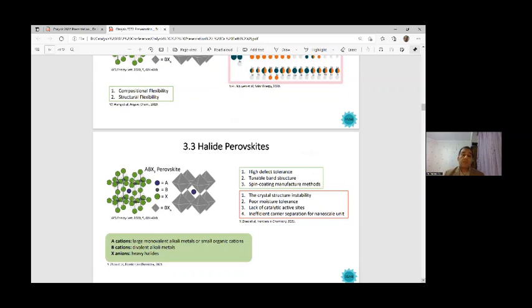On this page, you can see the chemical composition of a halide perovskite. These structures have advantages such as high defect tolerance, tunable band structure, and spin coating manufacturing methods. But in the meantime, we face challenges such as crystal structure instability, poor moisture tolerance, a lack of catalytic active sites, and inefficient carrier separation for nanoscale units. These are the disadvantages and issues we face with halide perovskites. In this structure, with chemical composition ABX3, A is a cation, large monovalent alkali metals or small organic cations. B is usually a cation, divalent metals, and X is usually anions, heavy halides.